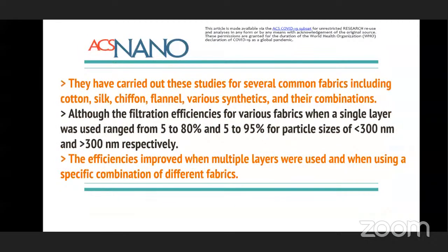These are their outcomes, that they have carried out these studies for several common fabrics, including cotton, silk, chiffon, flannel, various synthetic, and their combinations. Although the filtration efficiency for various fabrics when a single layer was used ranged from 5 to 80% and 5 to 95% for particle size of less than 300 nanometer and more than 300 nanometer respectively. So if size is more, efficiency will be more.